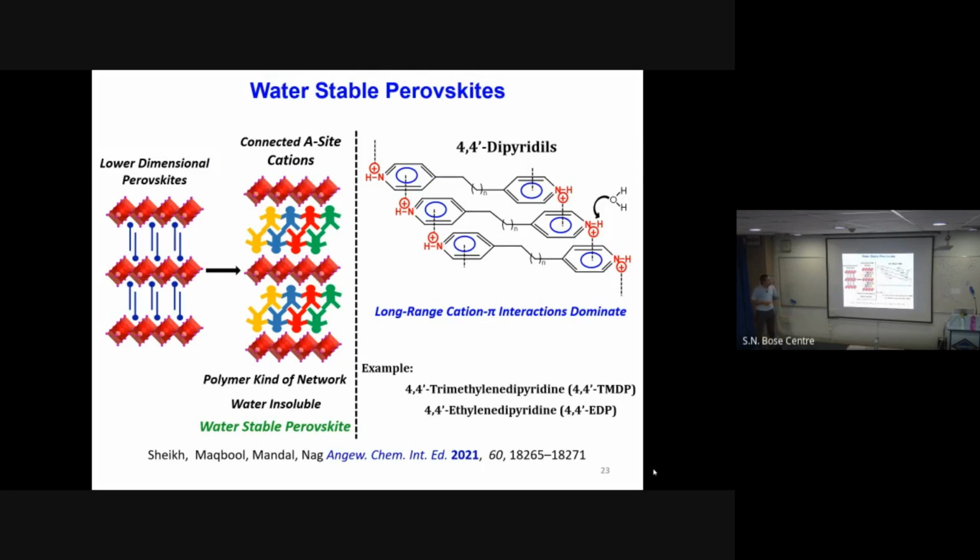So far I was talking about non-centrosymmetry, chirality, molecular intercalation, essentially designing structure property relationships, and we are tuning those relationships based on the nanoscale interface between the organic and inorganic part. Now, another problem in this field is the water stability. I mentioned that lead iodide is covalent, like when I talk about cesium lead iodide. So lead iodide is not really a problem. If you just make PbI2, in water it is reasonably stable. The problem is the third part, that is the cesium part.